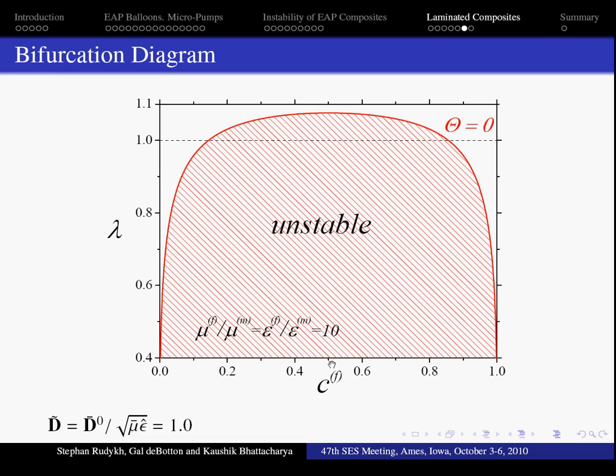And in the region, when inclusion and matrix volume fraction are small here and here, the composite is more stable. We know that for some values of volume fraction, mostly around C^f 0.5, the material becomes unstable even being pre-stretched.